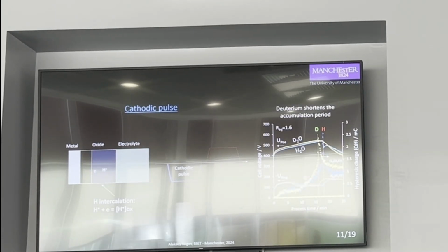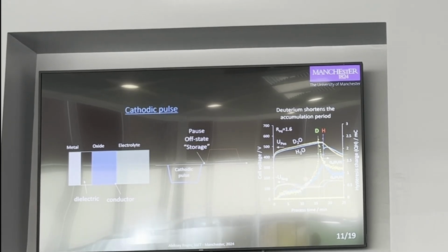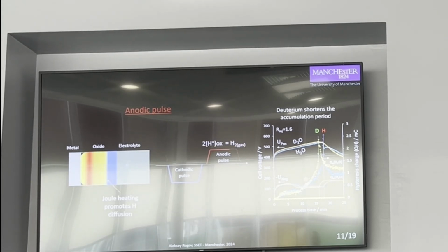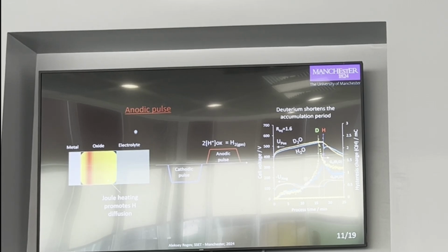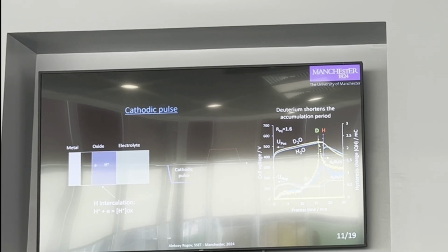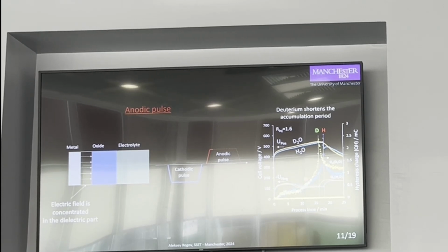Important additional information about why diffusion is the main factor here is the process's comparison for plasma electrolytic oxidation in proton-based and deuterium-based electrolytes. And in the case of deuterium, because of its higher molecular weight, we can see that soft sparking is achieved a little bit earlier because outward diffusion should be a little bit slower in this case.